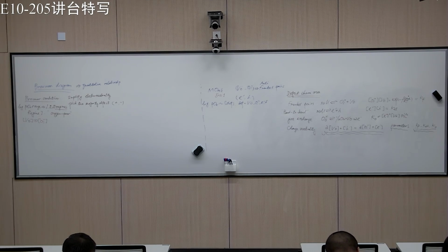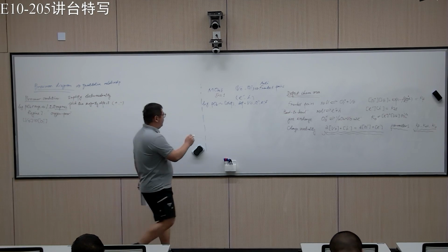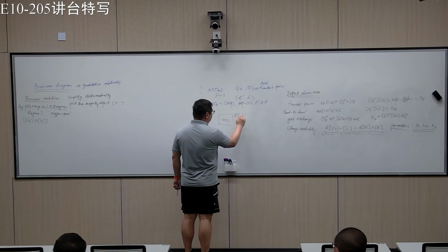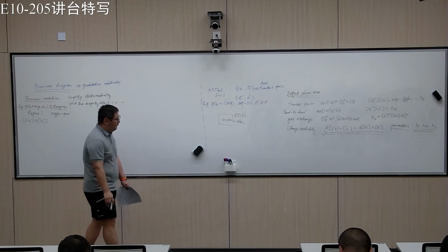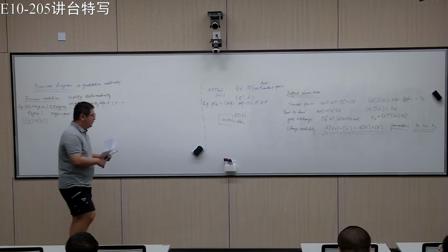Imagine that you have a system, let's say MO, and you lower the PO2 by a lot. Then oxygen gas will evolve, and you leave many oxygen vacancies inside the sample, and you don't have many oxygen interstitials. So let's go back to here.